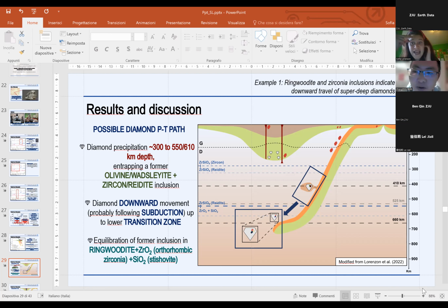And about the chemical composition, the carbon and nitrogen isotopic composition: yes, the carbon isotopic composition is quite homogeneous in the diamond, whereas the determination of nitrogen isotopic composition was more difficult, because if we have very low nitrogen content in our diamond, it's difficult to determine also the nitrogen isotopic composition. But all the significant results are positive.